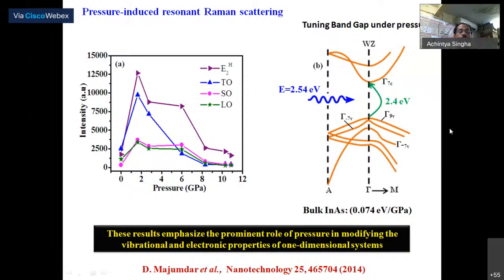On the left side you can see the intensity of the different Raman modes as a function of pressure. There we can see some resonant enhancement of the peaks. That enhancement is due to the resonance of the incident laser energy with the band gap of the system. In this way you can get band structure information from the Raman measurement. So this is the effect of pressure, and using Raman study you can get structural information as well as electronic band structure information.